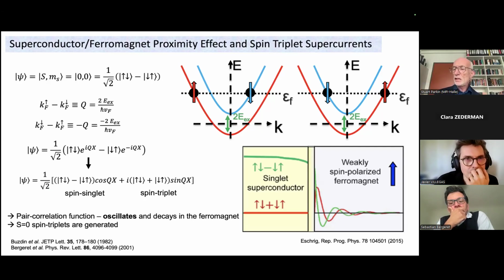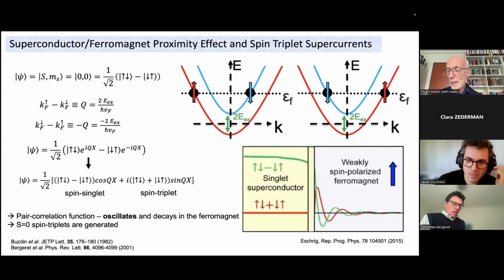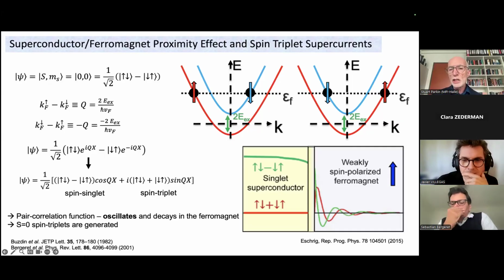Well, you're all familiar that in an S-wave superconductor, the superconducting condensate is formed from Cooper pairs. And the Cooper pairs have two electrons, which have opposite spin and opposite momenta. Now, what happens when you have a ferromagnet, as shown in this cartoon? You can see we have a blue and a red band that are split in energy for the spin polarized up and down spin electrons by the exchange splitting, which of course is the Heisenberg exchange within the ferromagnet itself. And so the higher the Curie temperature, the bigger is this exchange.